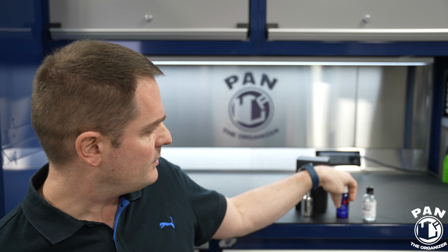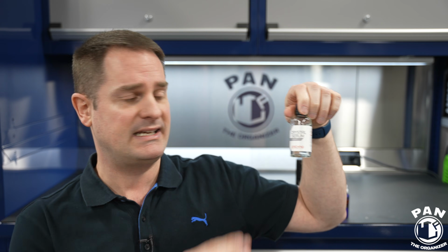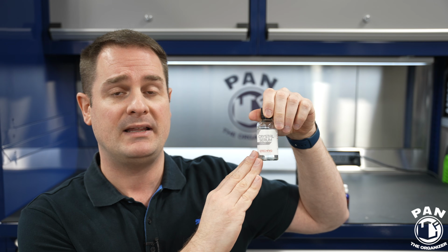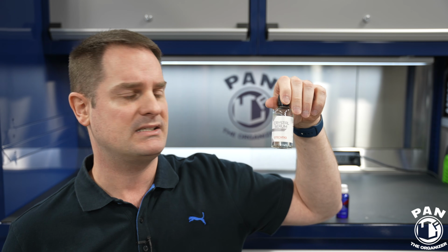Same thing applies for the CQuartz UK 3.0. They recommend a second coat for proper and even application of this. And you wait 45 minutes to about an hour between coats. For the Gtechniq Crystal Serum Light, this is a 1-layer coating. However, they recommend that you apply a topper on top of this, the Exo V4, 2 coats of that. So it would be a 3-layer system if you want to get the optimal conditions. And so there you go.